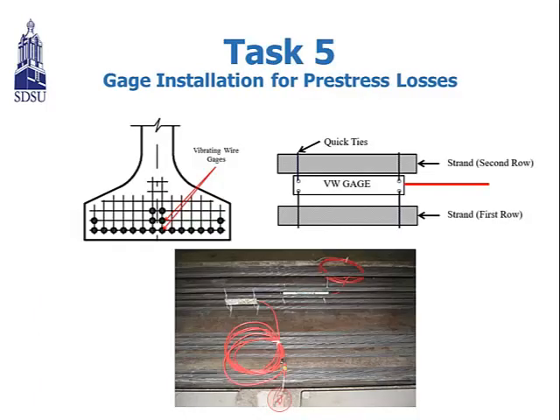And then we also need to measure the prestress losses. So we use mechanical strain gauges, and vibrating wire gauges in the middle of the girder, and then we conduct the long-term strain measurements. We measure the long-term strains.